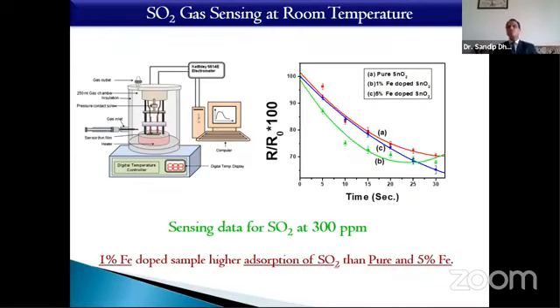But in sensing results, we found that this 5% sample is not giving very good results. Why does it happen? Because there is an optimum doping concentration. A 1% doping concentration gives you better adsorption of the gas entity on the surface, whereas 5% gives saturation, so adsorption is very poor in that case.